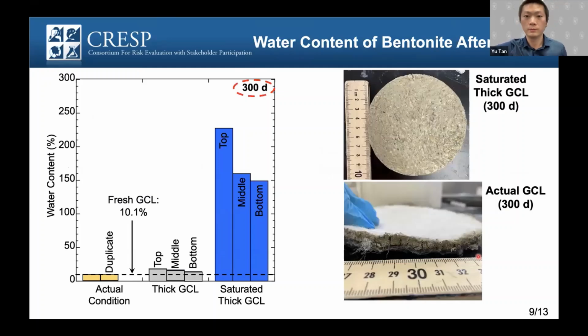So this is our result. First, we believe that the GCL will absorb water from the concrete to hydrate. If the water in concrete is calcium rich, it will affect the swelling and hydraulic conductivity of the GCL. So first we measured the water content of the GCL after 300 days of interaction. We just set up a column, let it sit for 300 days, took the sample out and measured the water content. The water content of the actual GCL is the same as the fresh GCL. Not much hydration happened.